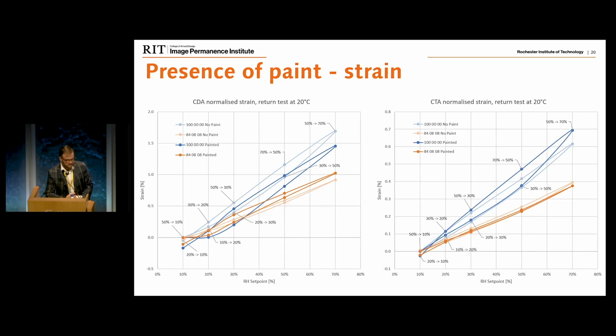Now, the last factor I promised in the beginning is the presence of paint. And here I'm using the two-way curves because A, I think they make nicer graphs, B, you've already been trained to look at them, and C, they actually show a very interesting effect. So, how to read them: the curve is strain going up and then going down. What you're seeing here is that the presence of paint slows down the initial process of humidification, but then very much speeds up the process of drying, to the point where those curves, almost all of them, I think, or if not all of them, actually miss their original 0.0.